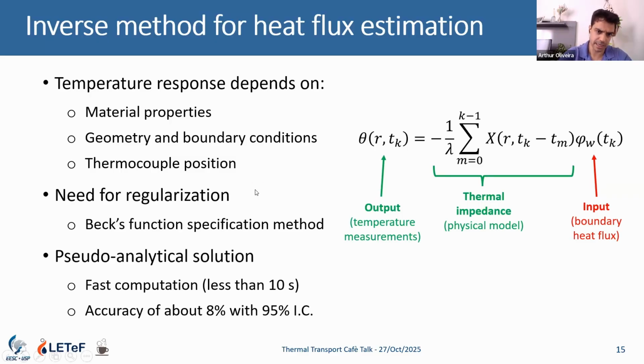There are several methods in the literature. We used Beck's function specification method, which gives us a pseudo-analytical solution for the heat conduction problem. The advantage of using a pseudo-analytical solution is that you have very fast computation of the data, and you have quite good accuracy compared to the results.